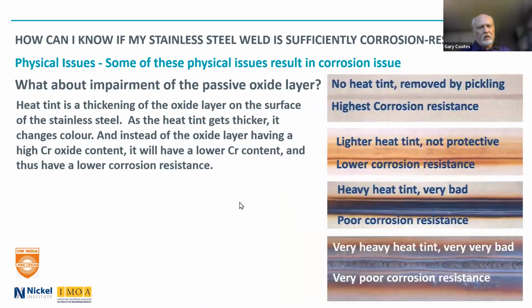So heat tint, which you get from welding, is a thickening of the oxide layer on the surface. And as the heat tint gets thicker, it changes color. And instead of a protective oxide layer on the surface that has a high chromium oxide content, it will have a lower chromium content and thus a lower, in some cases, a very much lower corrosion resistance.